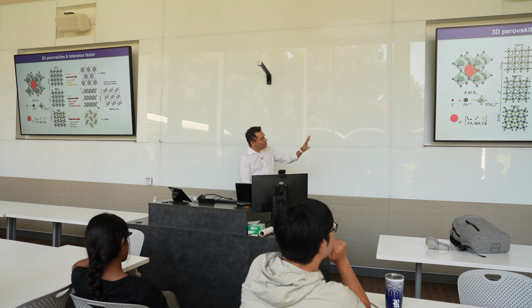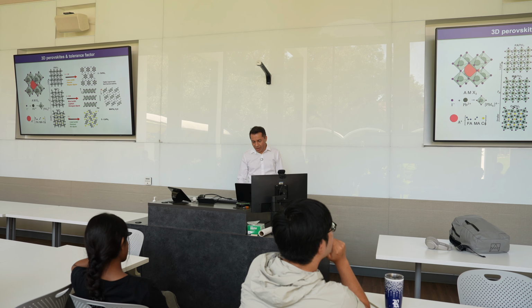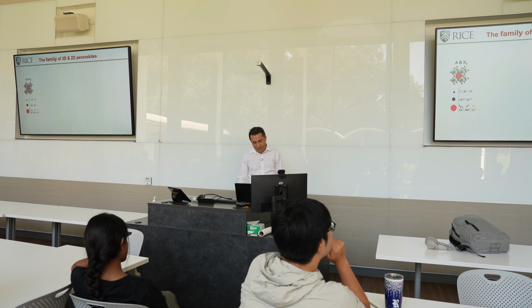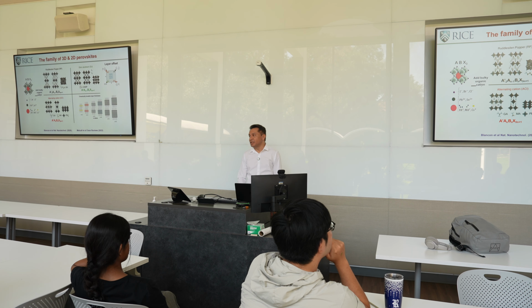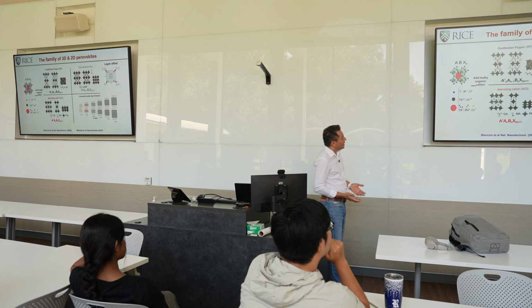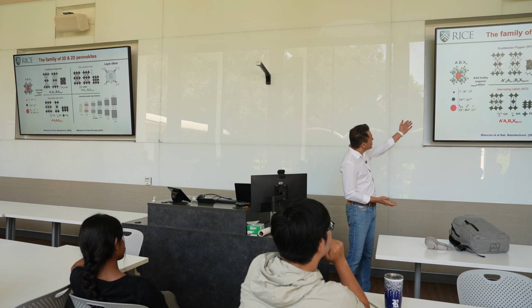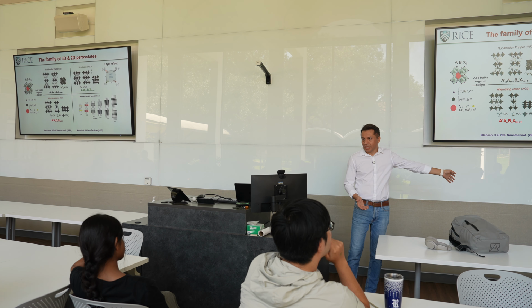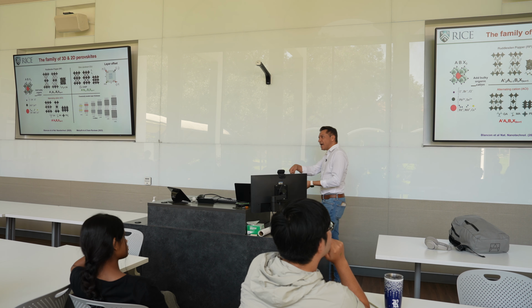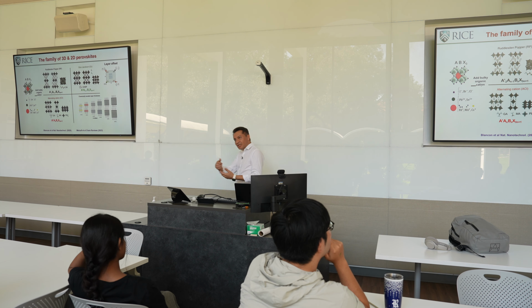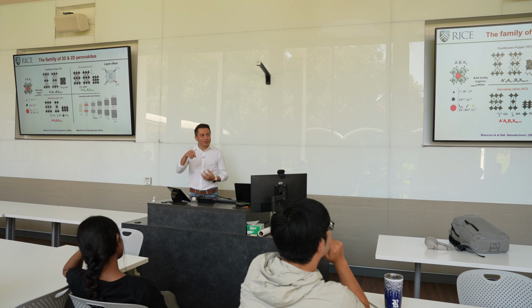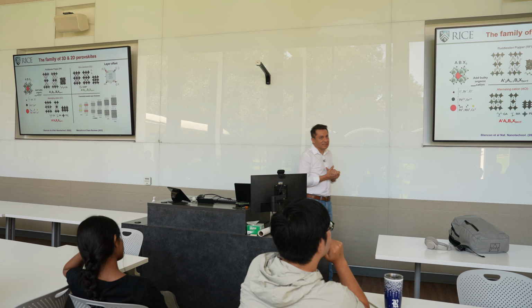So that's the thing, and so people do a lot of things around it. Now, in addition to this, there is also a family of layered materials, known as these two-dimensional perovskites, right? What you do is, I have the same perovskite octahedra, but I put an organic molecule that's much larger, so it can't really go into the lattice. And so what it does is assemble and form a layered structure. Okay? And so those are these layered perovskites.